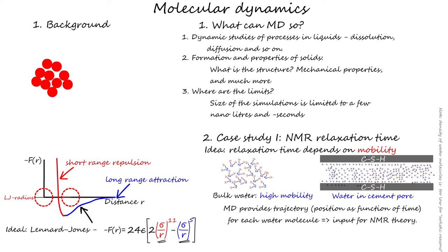Well, if MD were not too slow. The simulation of 1 nanoliter of water for 1 nanosecond takes approximately a week. In comparison, NMR relaxation times are in the order of microseconds. Thus, mobility data is required over such a long time interval, and Serge-Henri Akashia, the PhD student working on this, would never finish. This problem was overcome by combining molecular dynamics with another technique, Monte Carlo simulations.